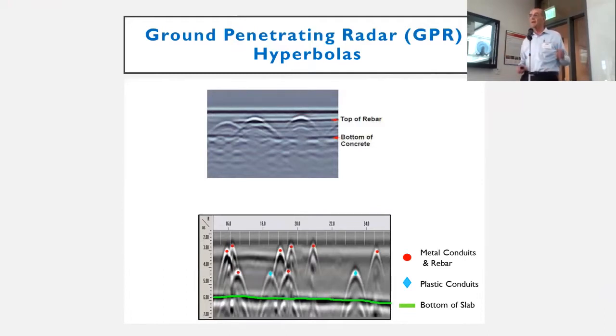We can just run a GPR, and where the change in color occurs, that tells us the thickness. Along here, the vertical axis, that is the thickness. So that is telling us, for instance, this first peak of the parabola is down about 2.9 inches. And that is telling us that the slab here at the bottom is 6 inches. Thickness of the slab or the wall is established with this GPR. So this is an extremely powerful tool. And we can also use it for other things like wanting to look for voids in concrete, which are not really that easy with the GPR, but it can be used to a certain degree. I can talk about that later on.